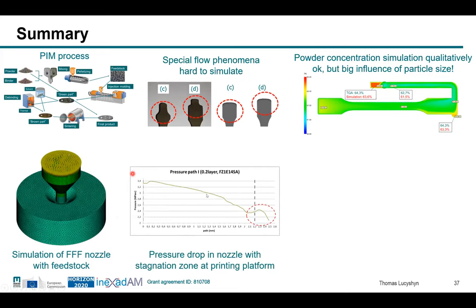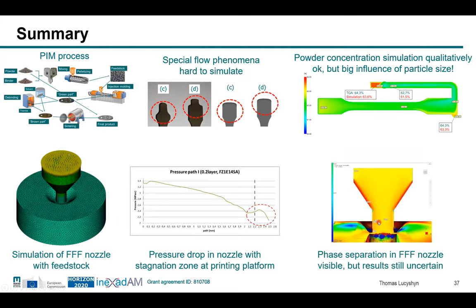One of the results was this pressure drop along the nozzle. So you can choose different materials. You can estimate how much pressure you would need to squeeze the filament through the nozzle. And I also showed you first results regarding the powder segregation, which is really important if we could simulate this, because if we know the correct powder concentration, this would give us some hint on where there is an agglomeration of powder, or the other way around, if there is an agglomeration of polymer binder, there will be a void in the final product if we remove the binder. So it's important to know if it's a very homogeneous distribution, which is desired, or if we have some spots where we have a higher concentration. It's still not perfect, but we are still working on this.